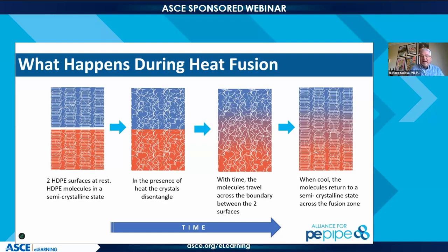And I can tell you with a high degree of confidence, I've done thousands of tensile pulls on various properly fused joints, and I've never had one fail in the joint. It's always failed in the parent pipe. So whether that adds to thickness, and that's bead removal as well, but it just goes to show that monolithic system does exist.